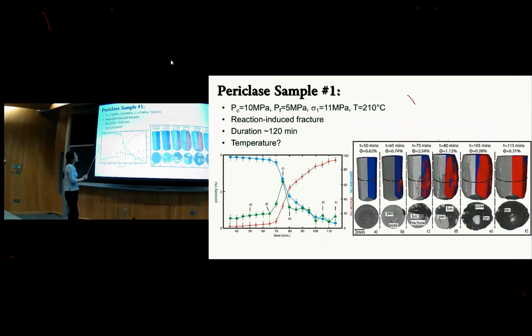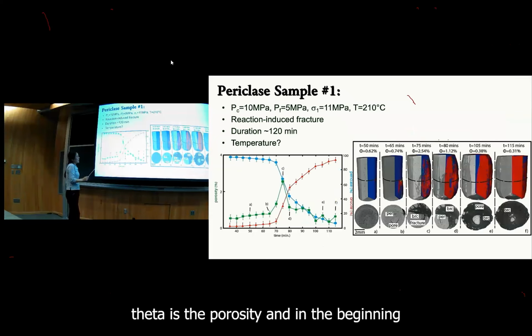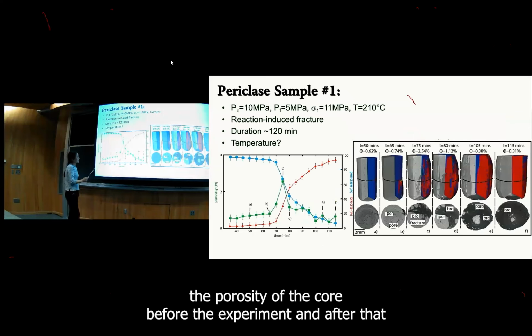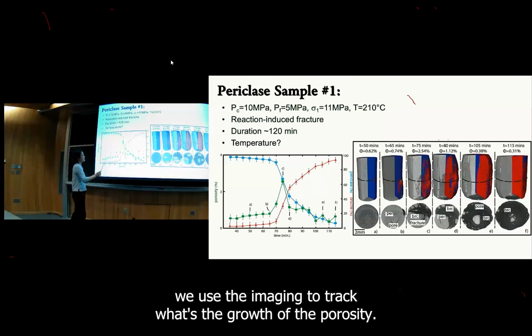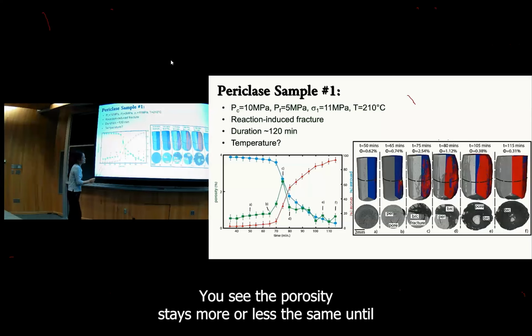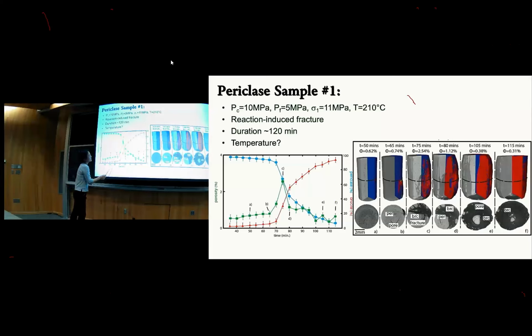The green data is porosity. At the beginning, the porosity is a little less than 1% in this case. We measure the porosity of the core before the experiment, and after that, we use the imaging to track the growth of the porosity. You see the porosity stays more or less the same until the peak. That's where the fracture started, all right?